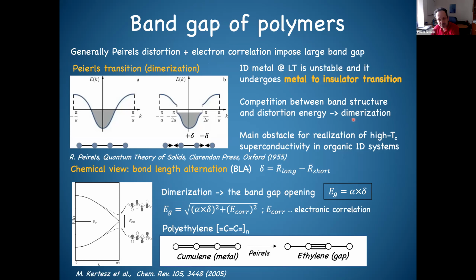The first is what we call the Peierls transition. This is the theorem which tells us that in 1D, if we have a half-filled band in a principally metallic system, this system is unstable and it undergoes some transformation, or dimerization. So it means that the distances are no longer equal. And this is very well known in chemistry, where we see that linear chains, for example the cumulene, which would be metallic, undergo, due to the Peierls transition, a transition and go to the ethylene. So then we have what we call the bond length alternation. And this bond length alternation somehow opens the gap.